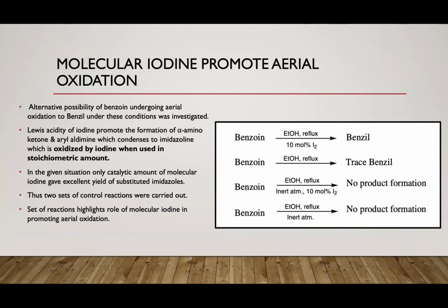After preparing the library of compounds, when we again tried to look for literature data, we could not find any paper where you can synthesize imidazoles from benzoin without the use of an oxidant. An oxidizing agent is required for that. So we tried to find out what significant improvement iodine has made. We carried out several control reactions, alternative possibilities were checked, and we realized that iodine is promoting the aerial oxidation of benzoin to benzil.